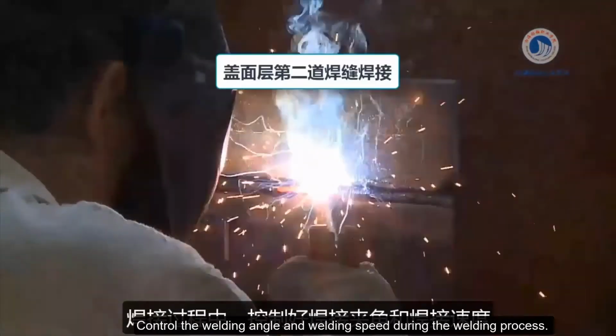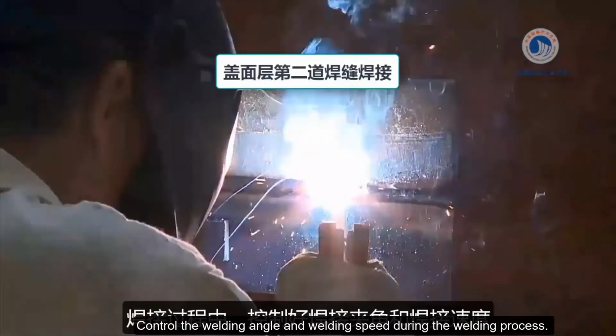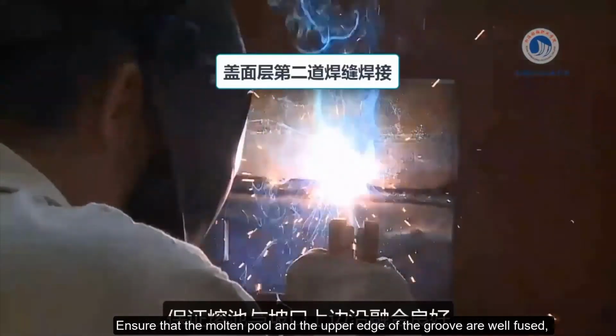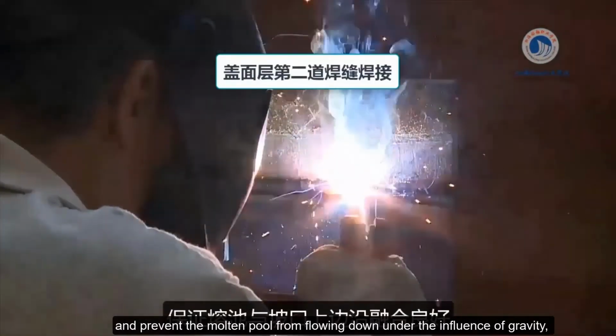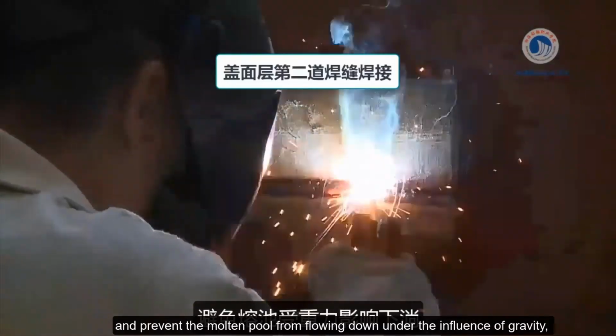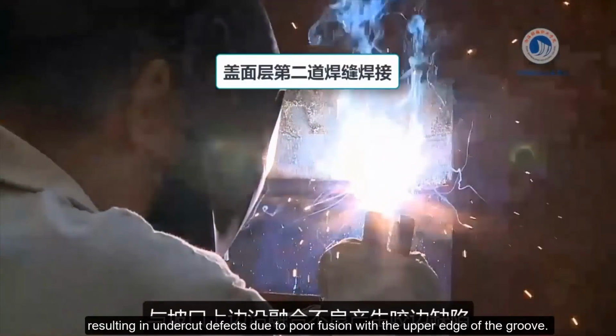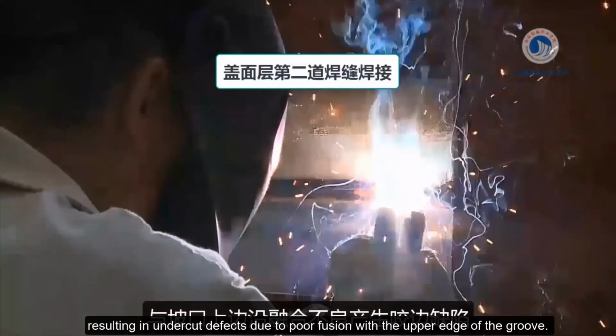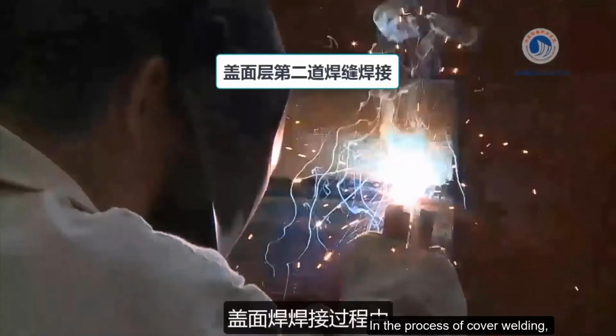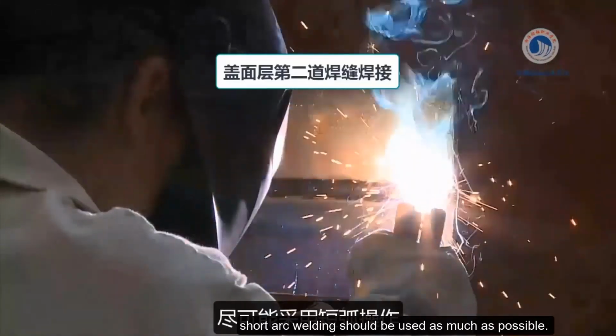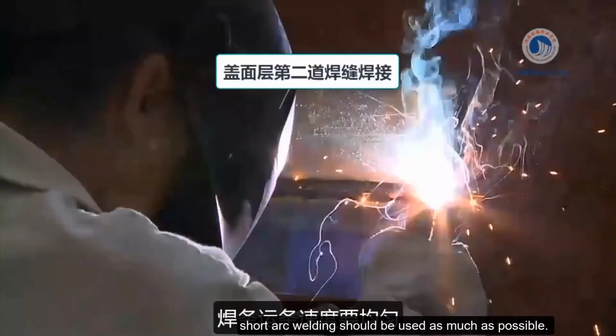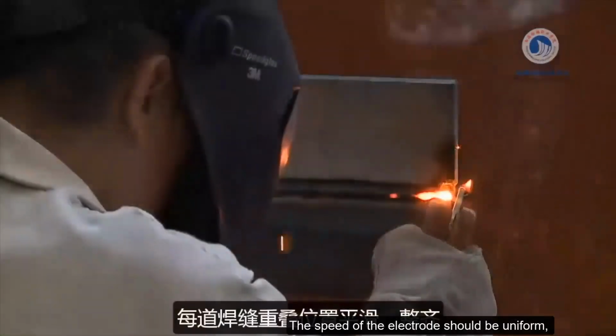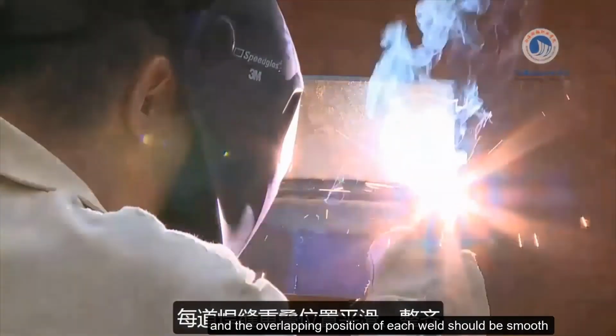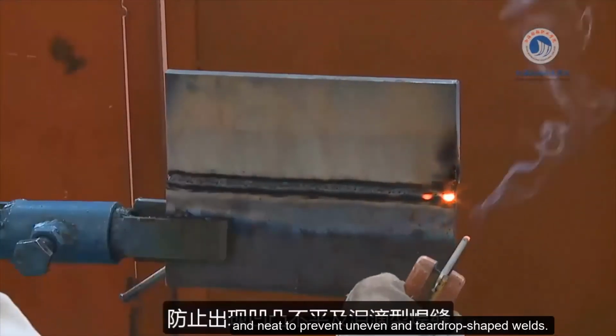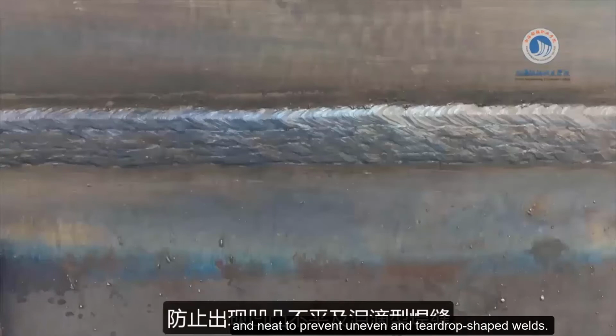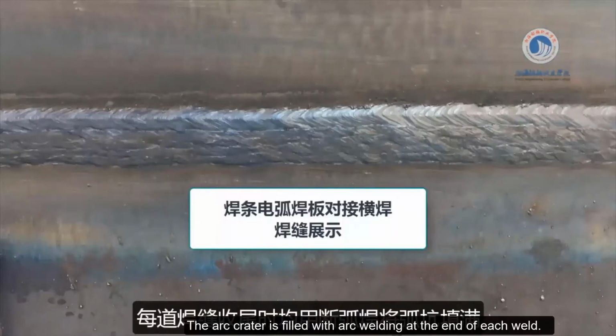Control the welding angle and welding speed during the welding process. Ensure that the molten pool and the upper edge of the groove are well fused, and prevent the molten pool from flowing down under the influence of gravity, resulting in undercut defects due to poor fusion with the upper edge of the groove. In the process of cover welding, short arc welding should be used as much as possible. The speed of the electrode should be uniform, and the overlapping position of each weld should be smooth and neat to prevent uneven and teardrop-shaped welds. The arc crater is filled with arc welding at the end of each weld.